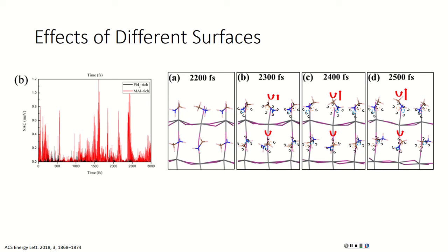So you see that the methyl ammonium over time will rotate up, and thus expand the octahedral cage that they're normally found in, or on the edges. That's really hard to see. You see these points right here. They become flatter right there, so there's probably less distortion on the cage, and that's what's creating these higher distortions of non-adiabatic coupling.